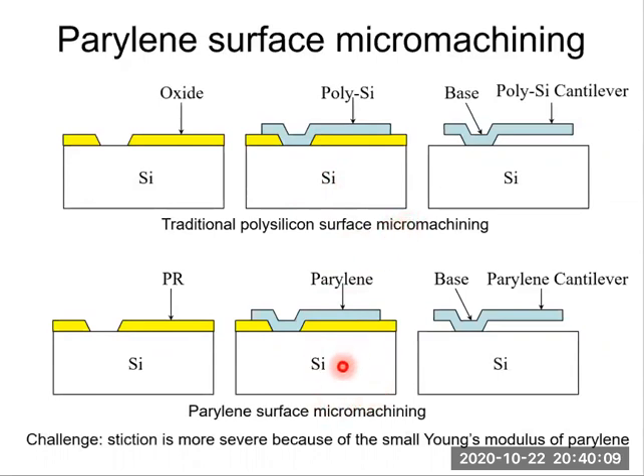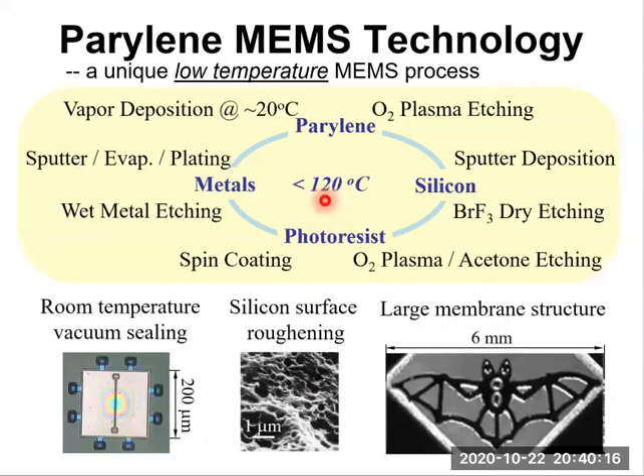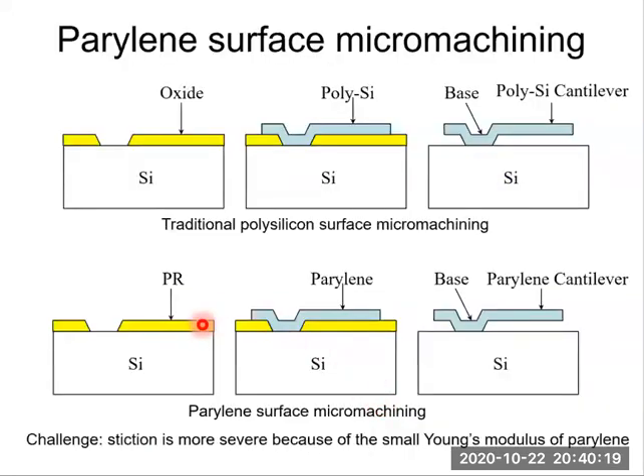micromachining. And for parylene surface micromachining, the process temperature is below 120 degrees C. The spin coating of photoresist occurs at low temperature. We need to bake photoresist. That process needs a temperature around 100 degrees C. Parylene is deposited at room temperature. So this is a low temperature process. In comparison, for polysilicon deposition or oxide deposition, we need a fairly high temperature.